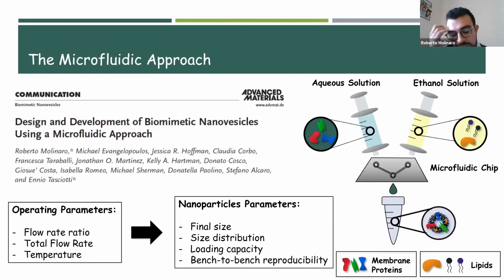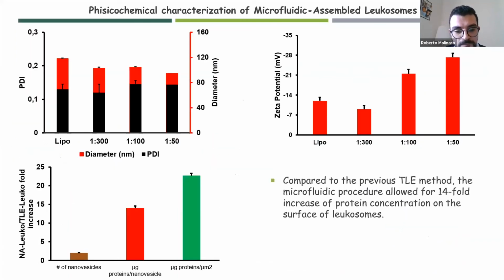In particular, by playing with the operating parameters like the flow rate ratio, the total flow rate, and the temperature, we could fine-tune the nanoparticle parameters: final size distribution, loading capacity, batch-to-batch reproducibility, and protein incorporation into the lipid bilayer.